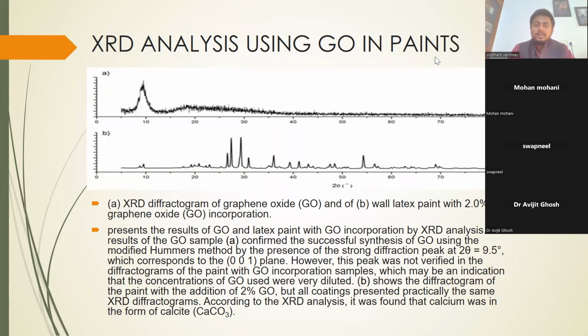XRD analysis is basically the peak. The lower the peak is, the higher the exfoliation is. So here in the A peak, you can see the first peak is somewhere around 9 to 10 degrees, that is 2 theta at 9 to 10 degrees. It's a low value, and graphene goes up to 28 degrees also. So the lower the value is, the better your graphene is, the higher the exfoliation.